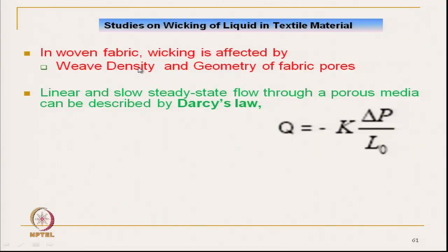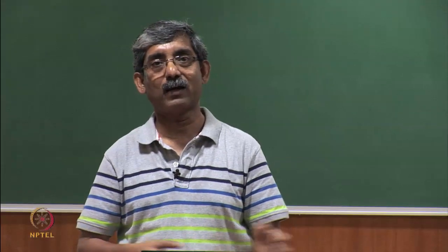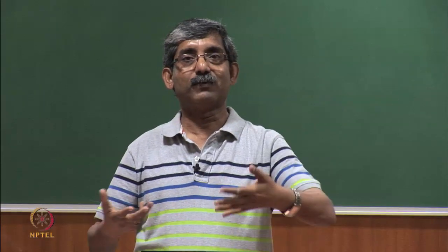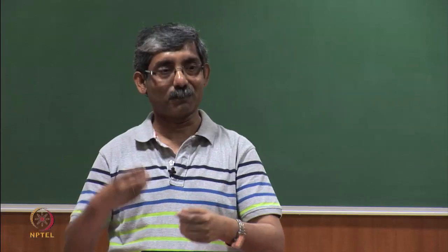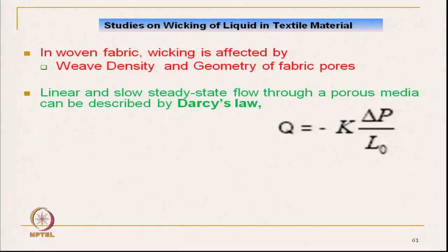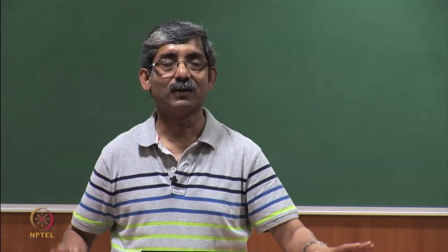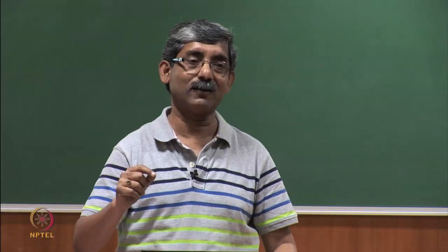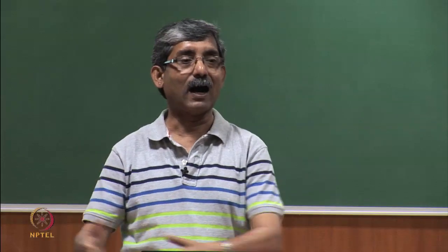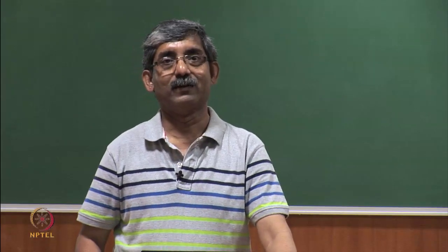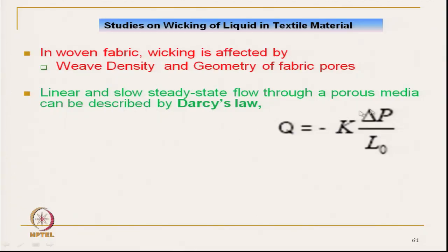Now in woven fabric, the wicking is affected by weave geometry and weave density. The density of weave, that is how compact the fabric is: if we increase the weave density, the yarns are close to each other, it will create capillary pores and wicking will take place. But if the fabrics are open structure, it will not be able to create the capillary pressure, and the wicking will be less. So, compact close woven fabric made of polyester filament will have a higher wicking rate than open structure. And linear and steady flow of fluid through a porous medium is described by Darcy's law.